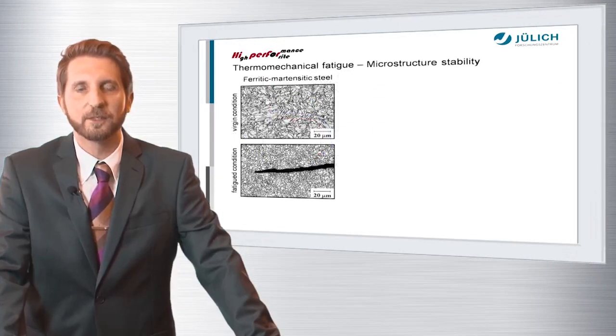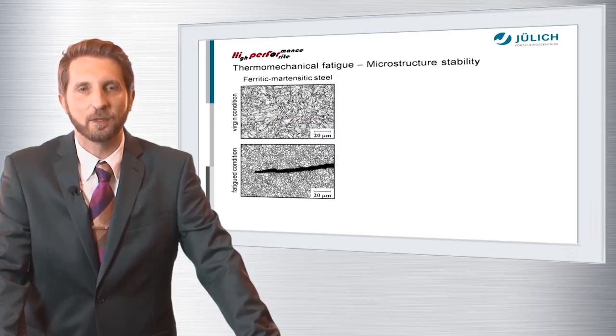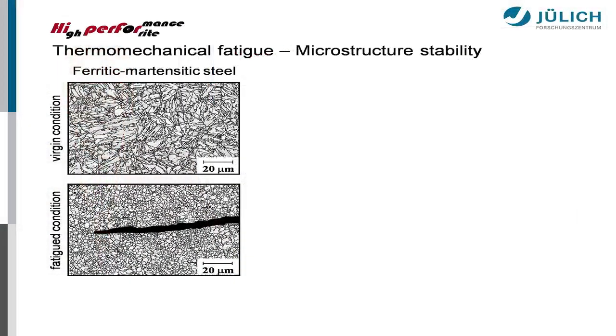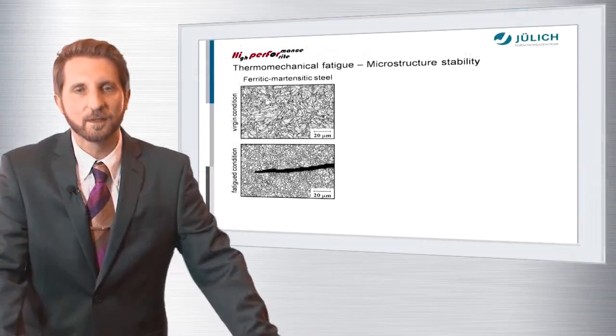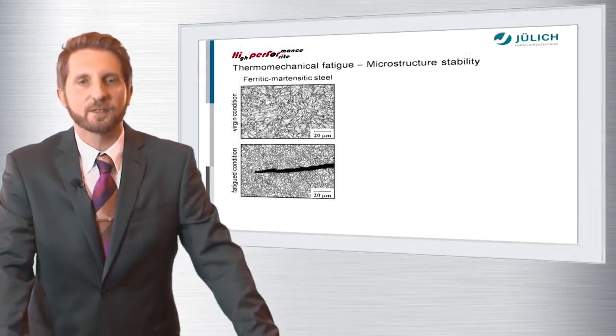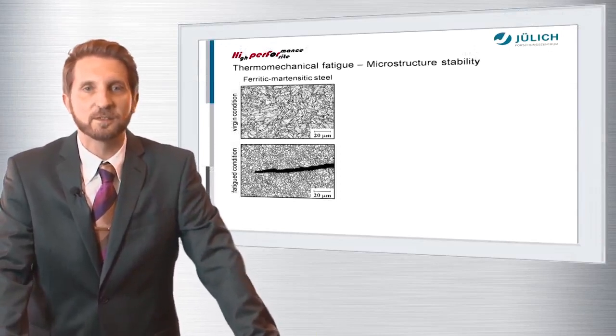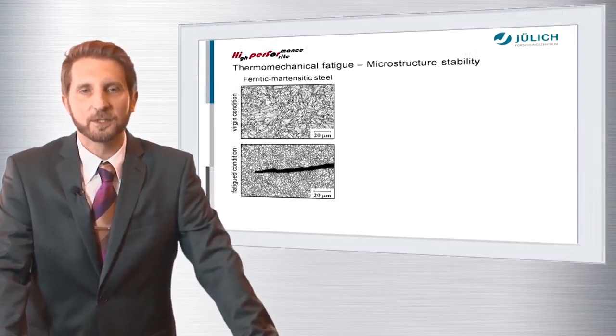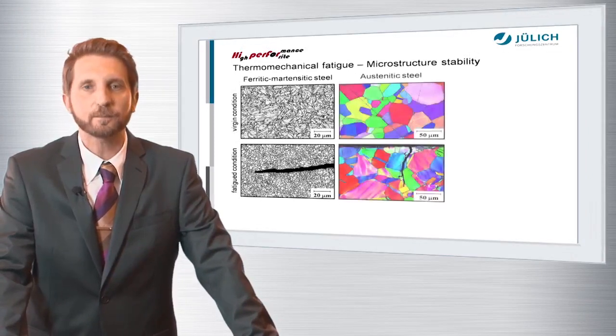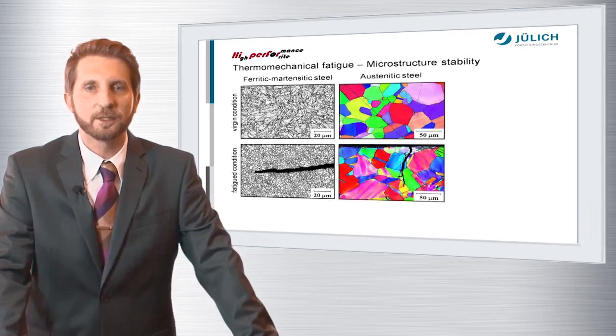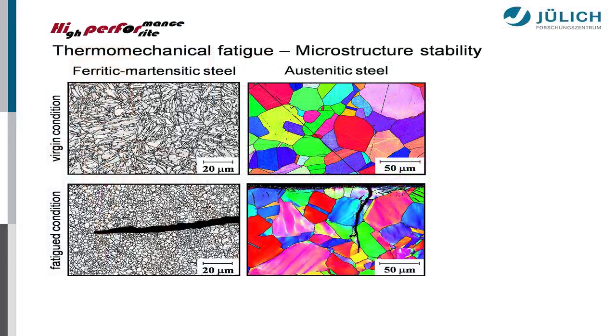And the microstructural reason for this behavior is the following. So if you take into account the ferritic martensitic steels, you can see in the virgin condition this well-defined martensitic microstructure, and in the fatigue condition depicted below, you see that this microstructure is completely lost. Ferritic martensitic steels suffer pronounced recrystallization in severe thermomechanical fatigue loading, which then later on causes premature failure. In case of the austenitic steel, such recrystallization does not occur. The grain structure is completely stable over the whole range.